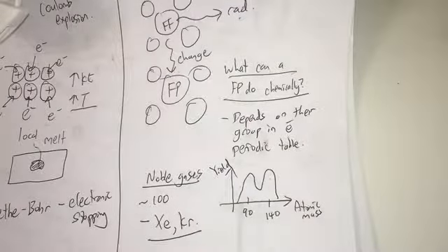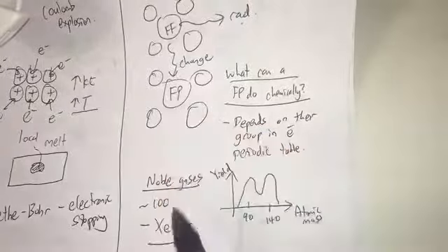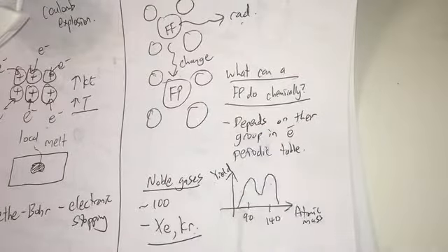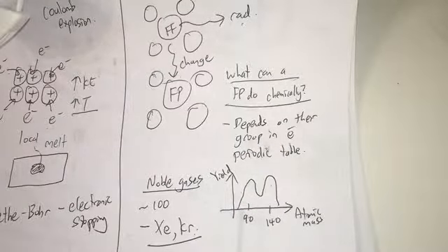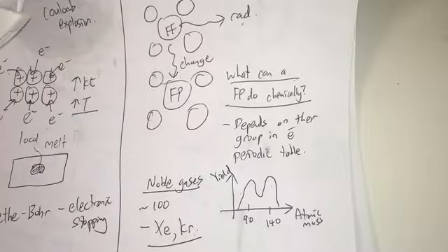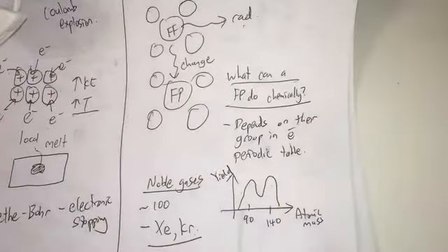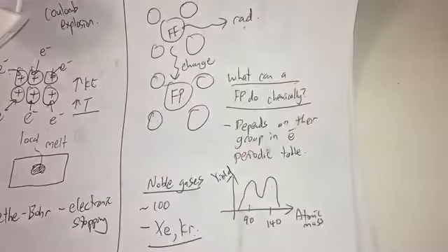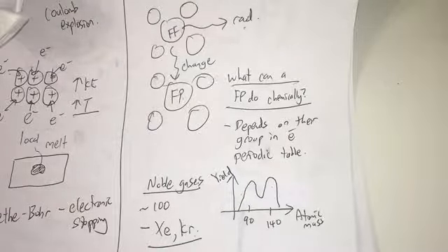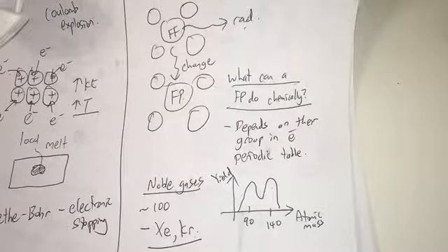They're pretty long term. So if this fission product is a xenon or krypton, what will you do? Well, these noble gases tend to be embedded in the fuel, and where do they go? They'll go near to the voids or the surfaces. So these guys will try and find voids in the fuel or vacancies, and they will tend to want to sit there. So they will migrate.